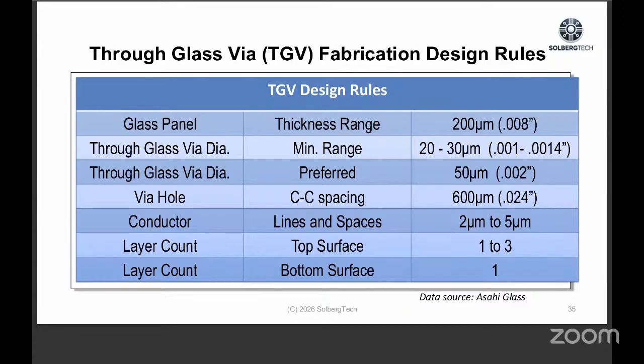As far as the via hole spacing, 600 micron. Conductor lines and spaces are 2 microns to 5 microns. Layer count 1 to 3. On the bottom layer is typically one routing because that's less density on the second level. Next slide, please.